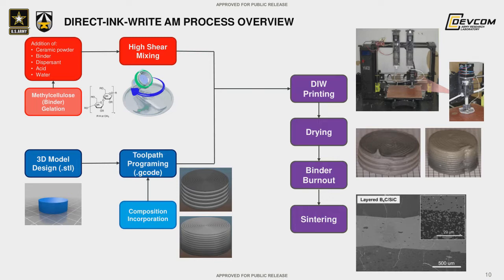On the bottom side, we have the design, which is where we start with a 3D model, typically an STL file, which is then converted into toolpath programming or G-code on the printer itself. And we have to do some custom incorporation of the composition information because there are limitations in the software's ability to deal with multiple materials within the same parts. So in this step, we have to manually go in there and insert the compositional information to the part in order to do things like functional gradients or discrete layers between boron carbide and silicon carbide.